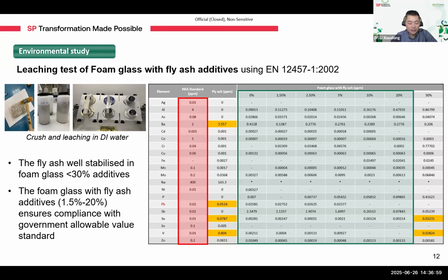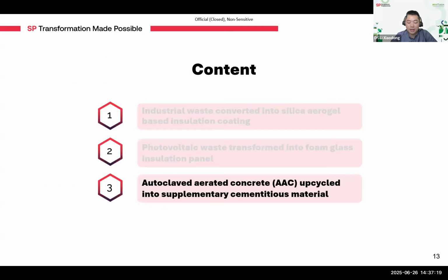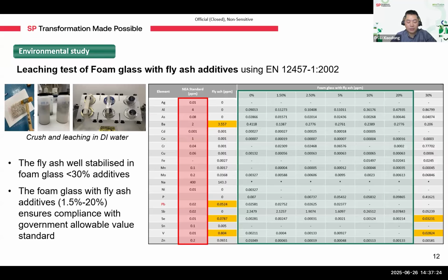The results are clear. Only the sample with 30% fly ash exceeded the allowable limits. For fly ash contents up to 20%, all the samples passed the leaching safety standards except for lead. So by pretreating the ash to remove the lead, it becomes safe to use, and the overall process becomes much simpler. So this project transforms end-of-life solar panel glass and fly ash into safe and high-performance foam glass insulation panels, offering a scalable and sustainable solution that supports circular economy goals and enhances building energy efficiency.